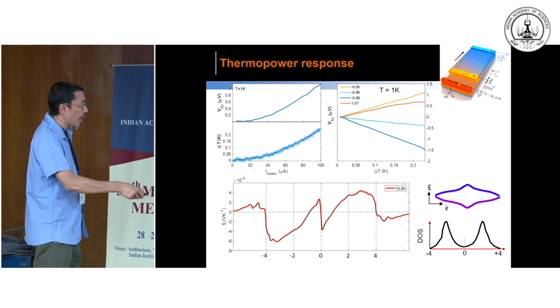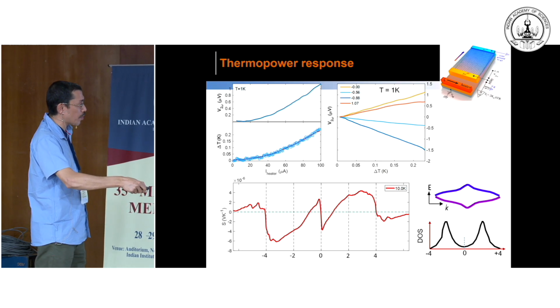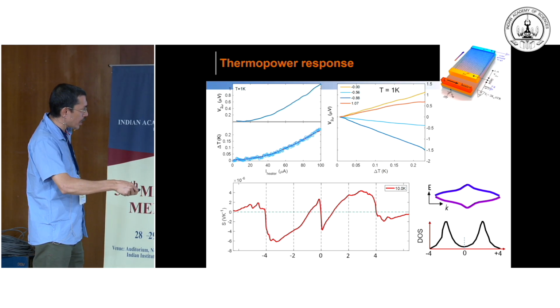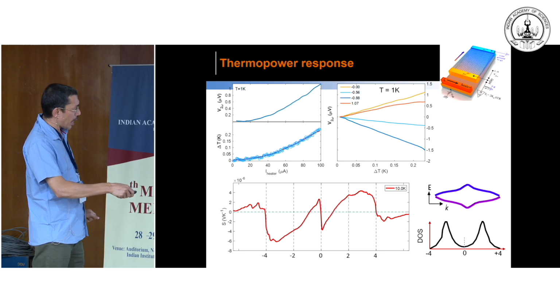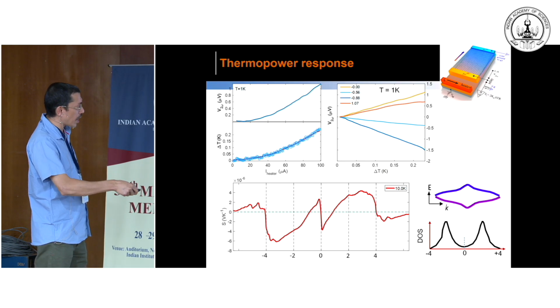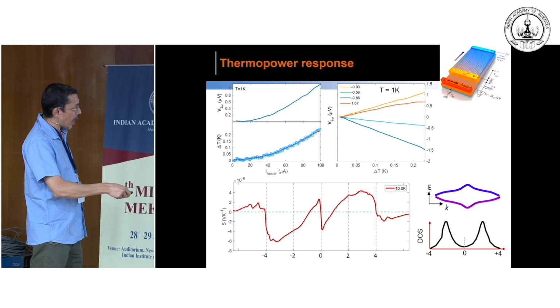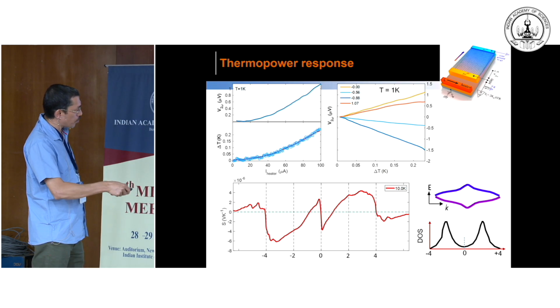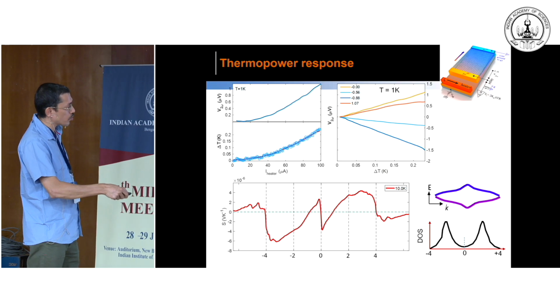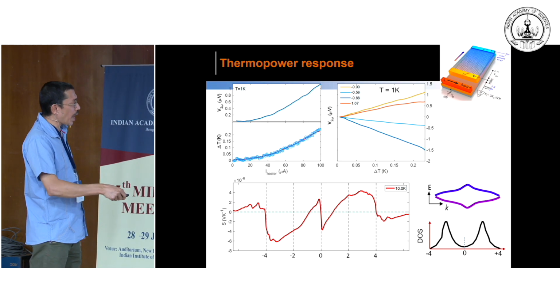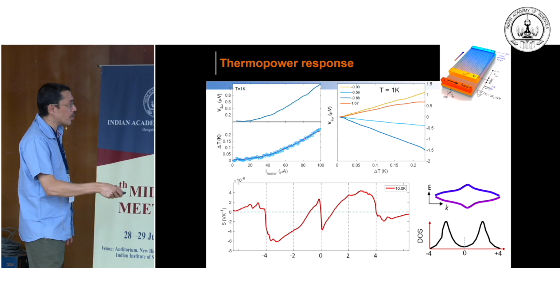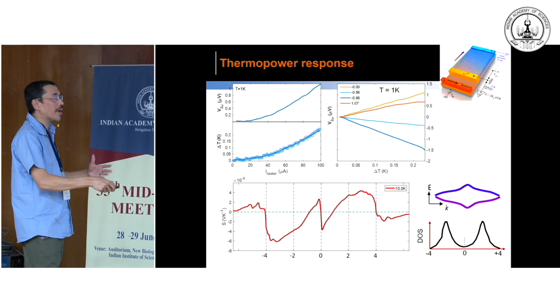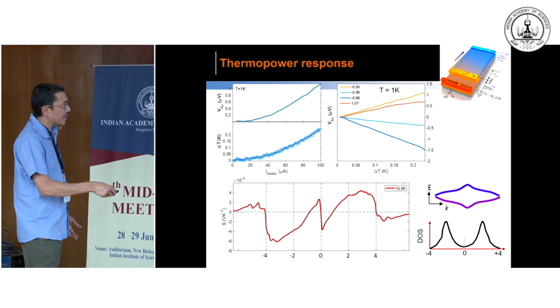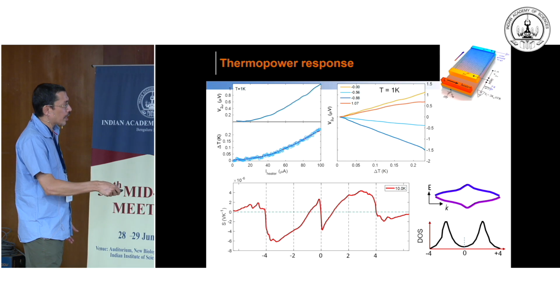To give you the band structure, if you have a single particle band structure like this, there are a few interesting points. Both the conduction and valence bands are quite symmetric, and at the Dirac point the thermopower is 0. Then there is another crossing, and at +4 and -4 you have another crossing because you are going from the flat band to the dispersive band. You can understand this at a qualitative level by the single particle picture, because at the Dirac point you will have particle-hole symmetry.